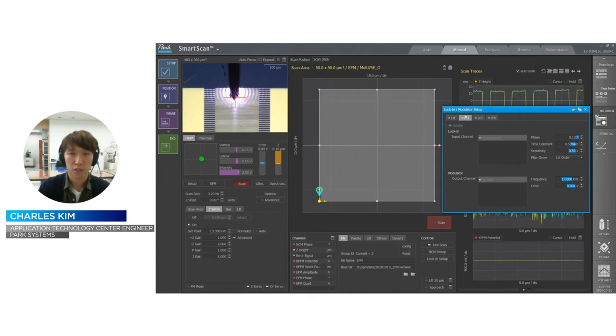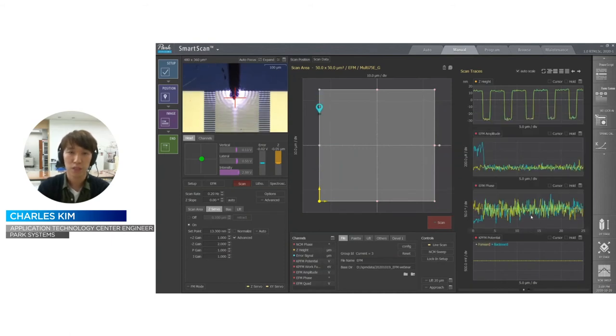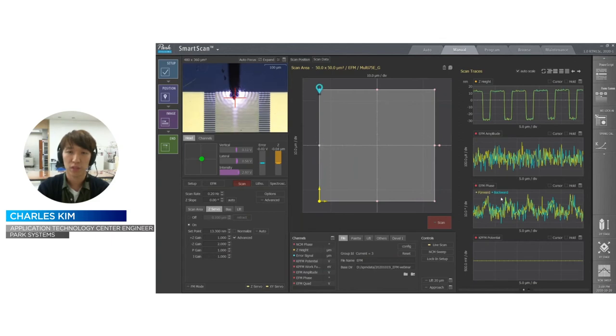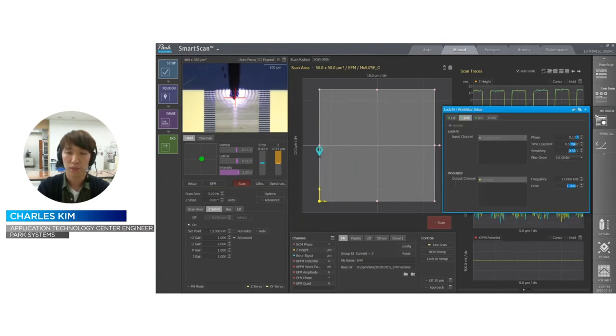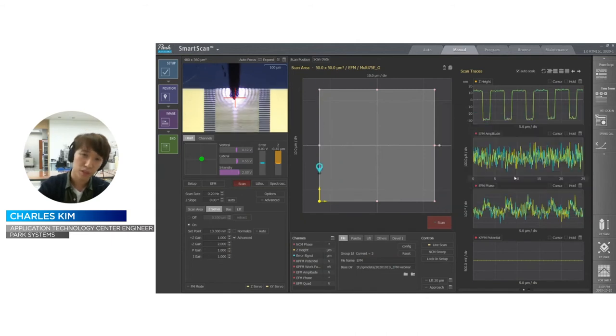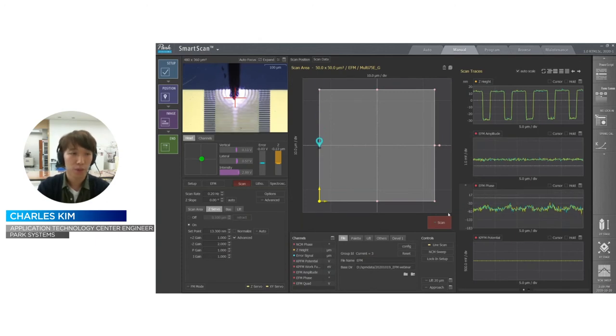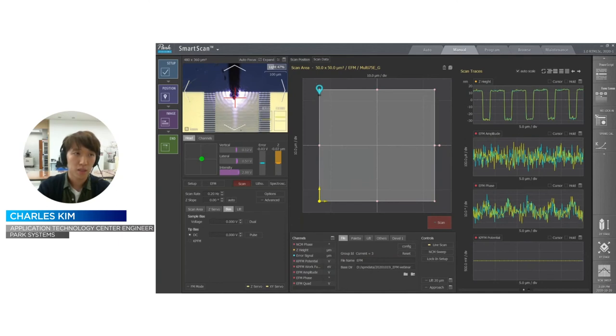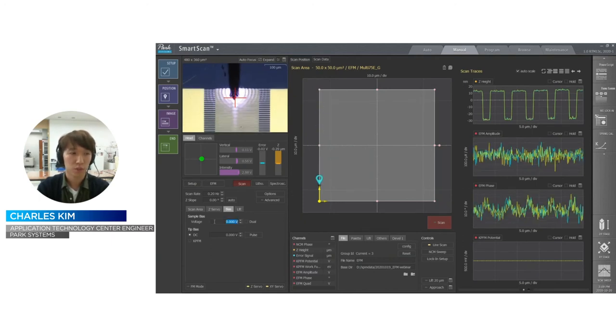As Dr. Kim already mentioned in the previous talk, we need to use the second lock-in amplifier. For the EFM, generally we use a 17 kHz frequency tip bias. So now the drive is zero. So let me give 1 volt of drive force. Then you can see something changing on the EFM amplitude and the phase. Now I apply the EFM modulation here, but still there are no specific changes because the left-hand side and the right-hand side are both zero now, because the sample bias is zero here. So please watch here. Then let me change it to 1 volt.